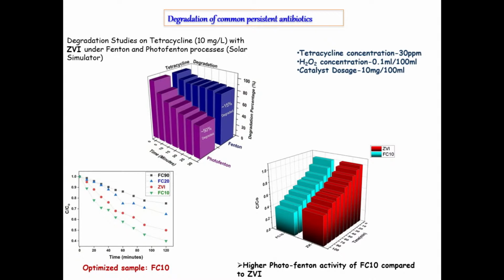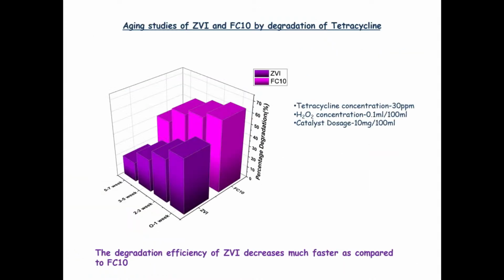If you see the activity, the photo-Fenton activity of the Fe-Cu heterostructure is much more as compared to the ZVI nanoparticles. So it's not just the activity being higher. When you do an aging study, the initial efficiency may be high, but you also see that the stability of these Fe-Cu heterostructures is much better. This work was carried out for about 7 weeks, and it shows much better stability for a tetracycline concentration of 30 ppm.